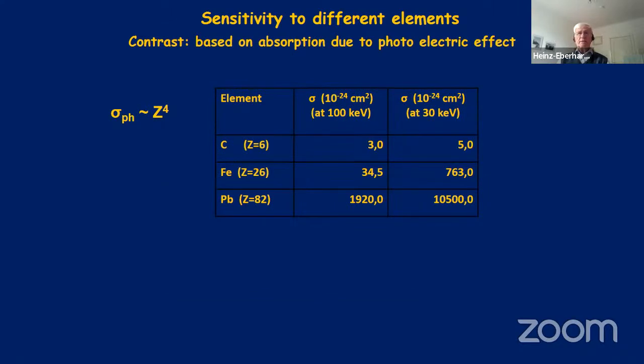The point is that the cross-section, as I mentioned in the beginning for the basics, depends heavily on Z to the power of 4. And here's a comparison between carbon, typically the constituent of an organic material, or carbon ink, for example, or iron or lead. If we go to 30 kilo electron volt, then we get a drastic change from Z equals 6 for the carbon up to Z equals 82.